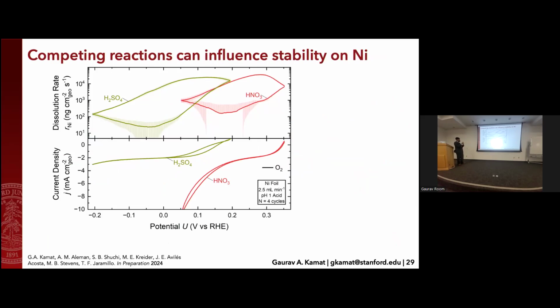So without any additional information, if I looked at this, I would say, well, nitric acid has a much higher onset for the ORR because there's oxygen present. And it does have maybe similar or higher dissolution in some areas, but it's at a much higher potential. So that looks really good.